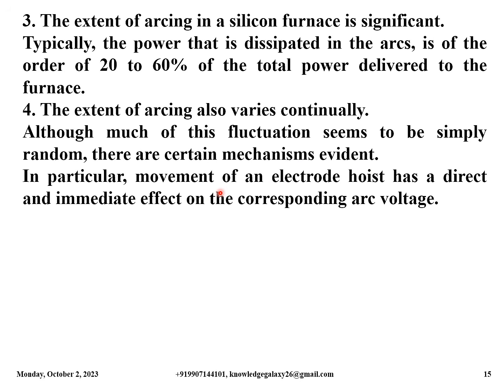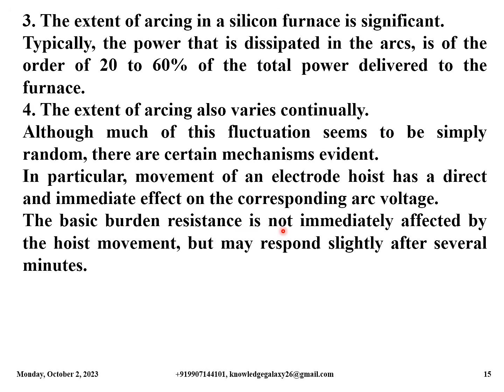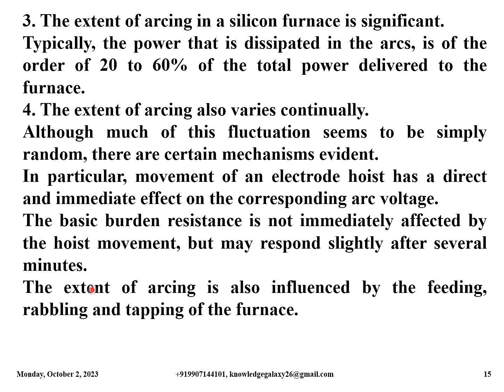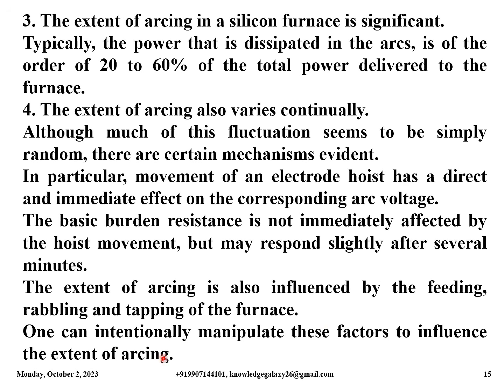In particular, movement of an electrode hoist has a direct and immediate effect on the corresponding arc voltage. The basic burden resistance is not immediately affected by the hoist movement but may respond slightly after several minutes. The extent of arcing is also influenced by the feeding, rabbling and tapping of the furnace. One can intentionally manipulate these factors to influence the extent of arcing.